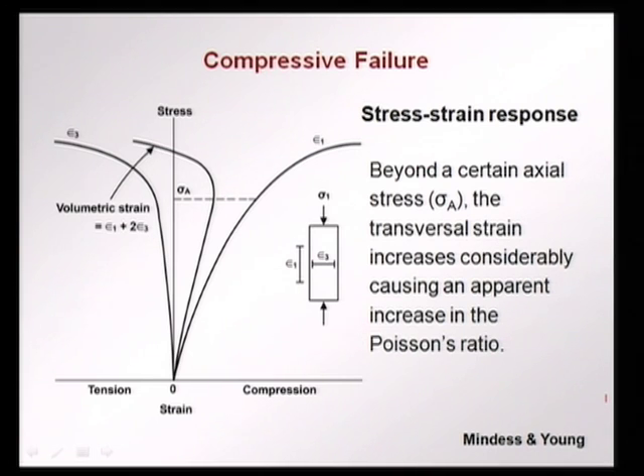Another important aspect which governs structural design and how concrete fails is what happens to the transversal strain and the volumetric strain. So, in the stress strain diagram, now if we have an axially loaded case, say we have a cylinder under uniaxial compression loading, and we look at the axial compressive stress, this would be the curve. The stress increases as the strain increases, we pass the linear part, we enter into a non-linear part, and then the peak. Now, if we look at the lateral strain or the transversal strain, we find again that there is a linear part, and then beyond a certain point there is a very large increase in the lateral strain.